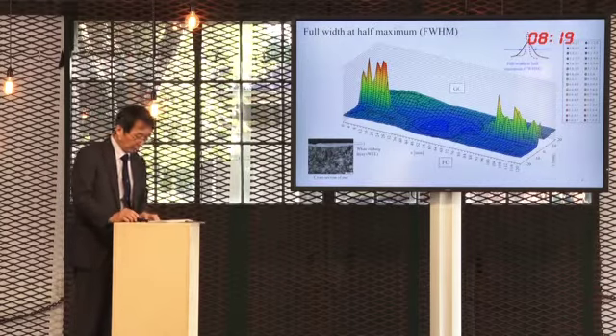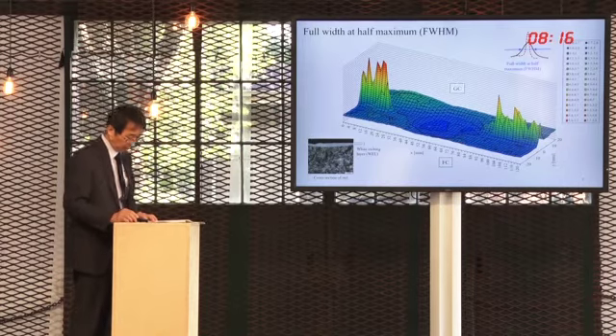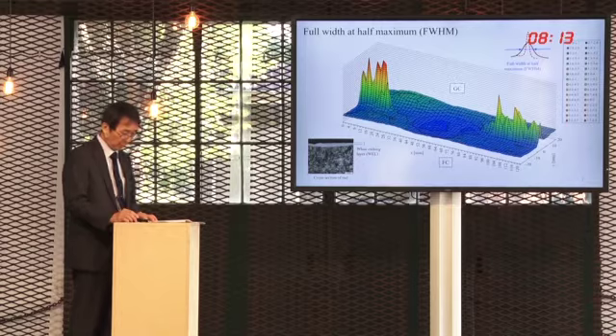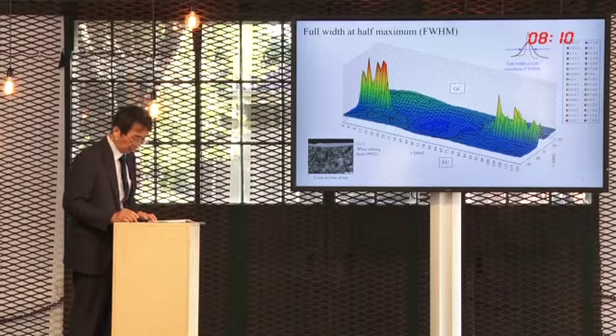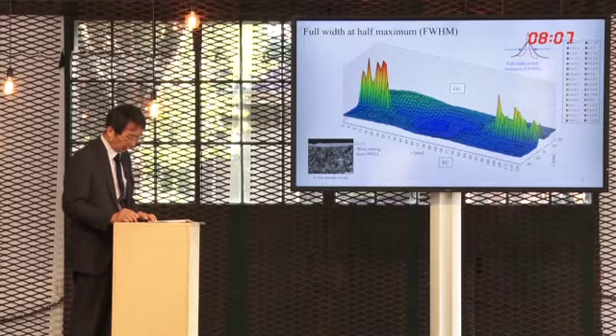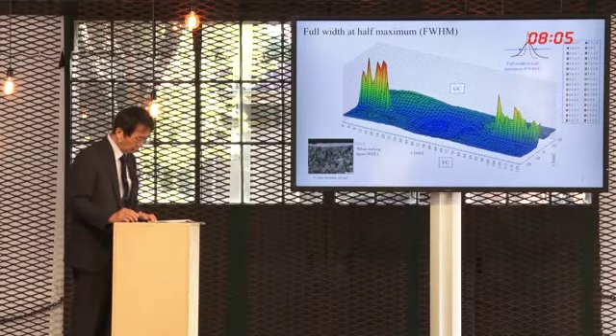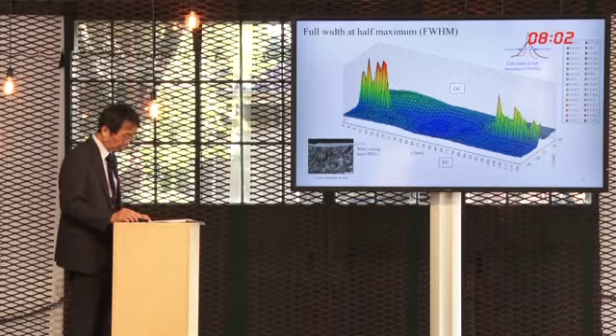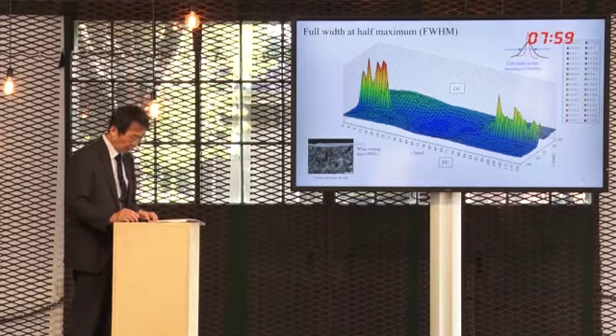This slide shows the 2D mapping of the FWHM, the full width at half maximum, obtained from the rail. The definition of the FWHM is shown here again. This plot consists of all data measured from 1,220 points. As a result, we can see that there are 2 sharp peaks on both sides of the graph. The place where these peaks were generated is consistent with the place where the white etching layer was generated.